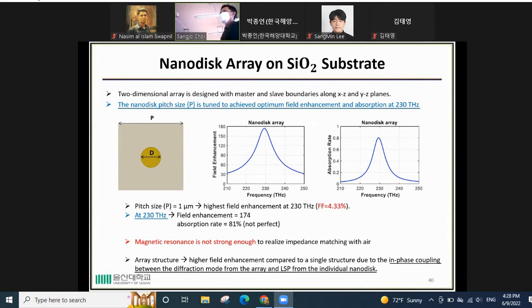So we can see high field enhancement at 230 terahertz with a filling factor of 4.33%. The field enhancement is 174 with an absorption rate of 81%, which is not perfect. That means the magnetic resonance is not strong enough to realize the matching with the air. You can also see the array structure has higher field enhancement compared to the single structure because of the in-phase coupling between the diffraction mode from the array and the localized surface plasmon from the individual nanodisk.